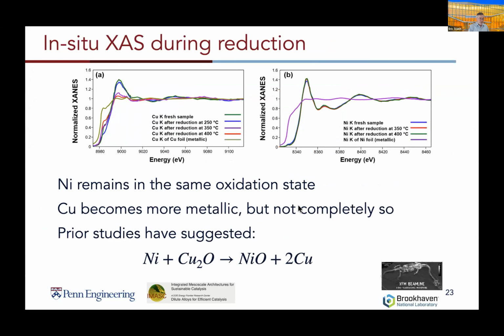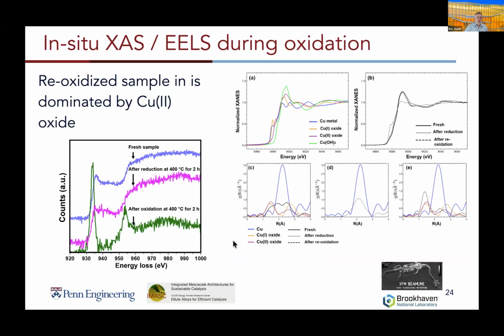So we can go through and again do the reactions, holding them at high temperatures. We find that in doing so, the nickel does not change dramatically during reduction, but of course, as expected, the copper does become more metallic, but not all the way towards the state that's present for the copper metal. In other work, people have indicated that if you reduce nickel-copper alloys, you're going to end up basically creating a structure like this, where nickel and the copper oxide will reduce to nickel oxide and copper. And so we'll talk a little bit more as we go further about that reaction.